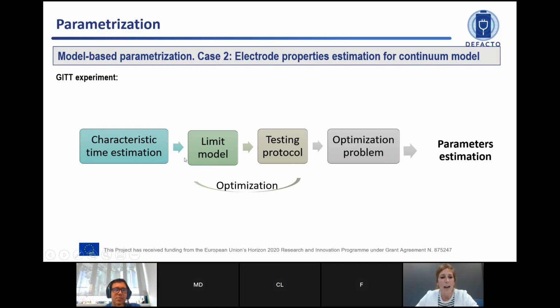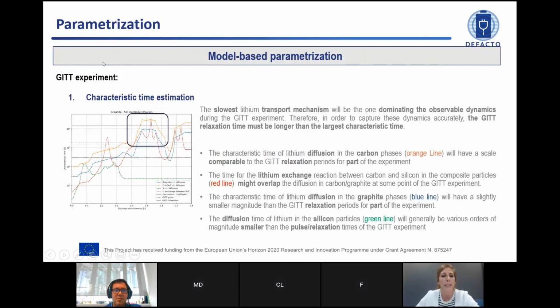So here, what we have pursued is the following method. First we quantified the characteristic time of each individual mechanism and compared it to the characteristic time of the relaxation period in the GITT. Considering the results of the characteristic times, we built a limiting model. And with these models, we compared to the testing protocols. Then later we implemented a quasi-Newton approach for the optimization problem, and later we estimated parameters. So here, what we did is, as I said, calculate the characteristic time. And what we have is the time related to the relaxation, with this black plateau line.